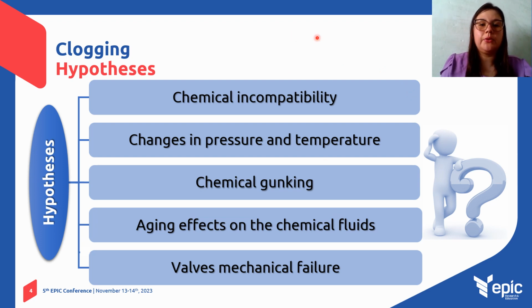Also, changes in pressure and temperature along the chemical injection system might induce precipitation or even chemical gunking, in which the evaporation of fluids can form a viscous semi-solid material that can also absorb solids in its composition. The chemicals injected also might not be totally stable at the injection conditions and suffer from some aging effects of chemical degradation. As the last hypothesis, valve's mechanical failure can cause backflow of the chemical injection valve, and possibly there might be the clogging issue from this problem.